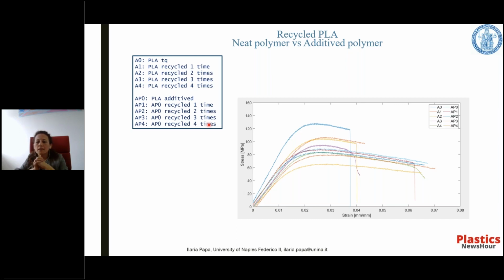Also in this case, for the additive manufacturing technology, we can see a decrease of all mechanical features, as we can see in this slide, as the number of recycling cycles increases. In particular, we have a lower value obtained by the additive ones, but a higher strain indicates less propension to damage of these components.